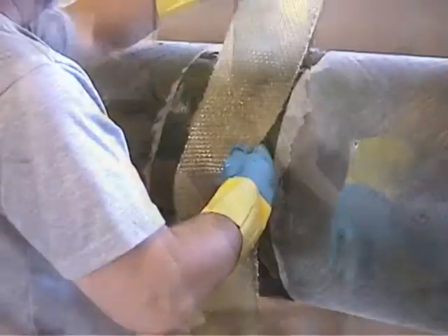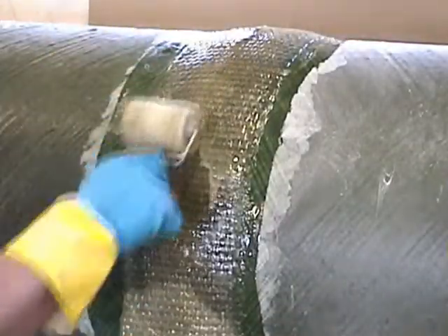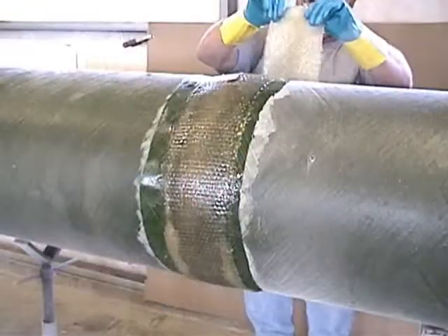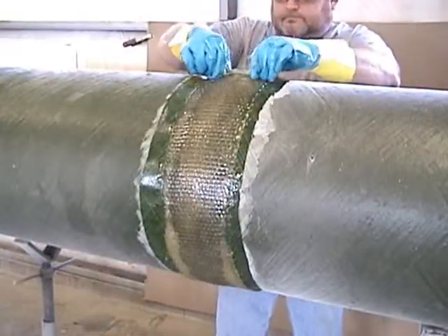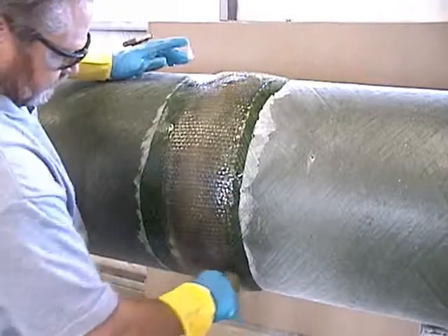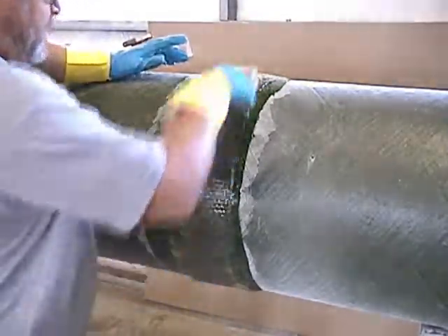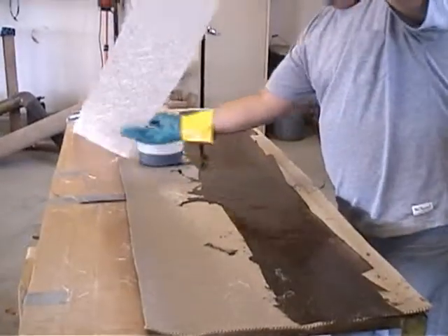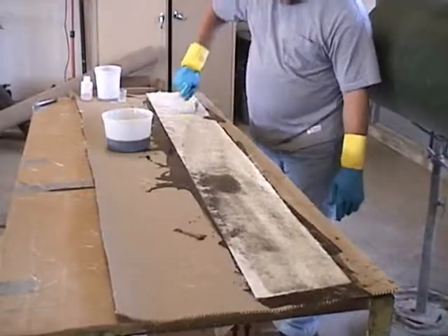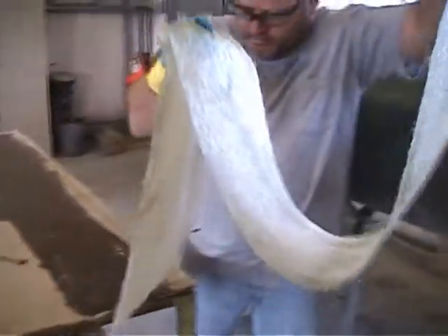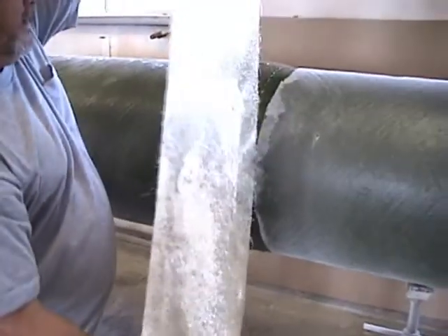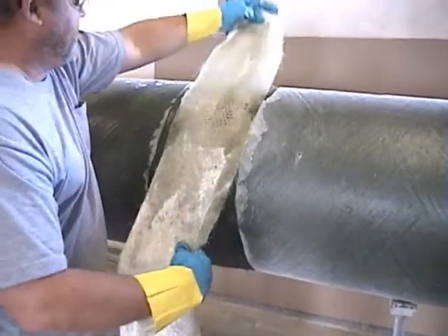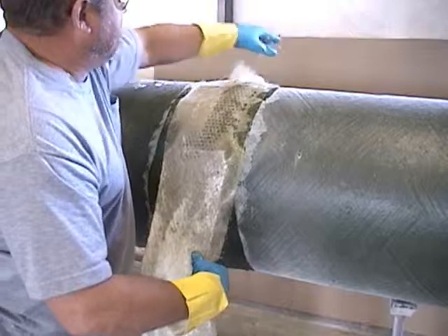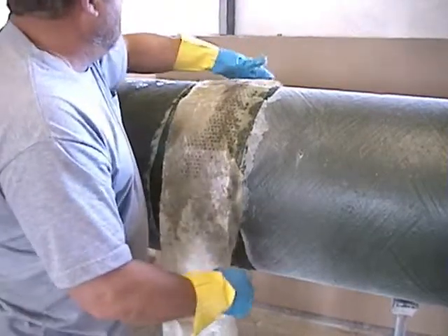Then we put 2 of these layers on the pipe, remembering to center them and to stagger the joints by about 3 inches. Even though we're not showing application of the 4th layer, you will wet and apply it the same way as this one. Wet the last glass layer, which is the cover mat. Don't get this layer too wet, or it will fall apart on you when you try to apply it to the pipe. This last layer is the widest layer, so it covers up the woven.